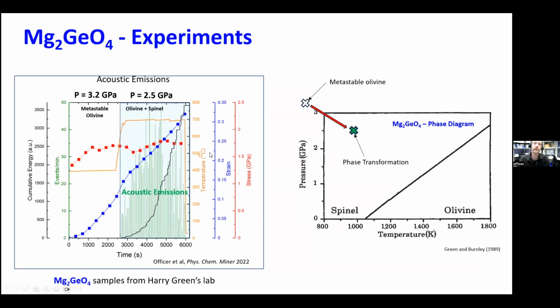So here's an example of a typical Mg2GeO4 experiment. This is one that I ran, but Alex Schubnel was the first to do this in 2013. So I don't want to say that this is the first time this has ever happened. But basically what we're doing is we bring it up to pressure, about 3.2 GPa, and then we've heated it up to 400 degrees Celsius. The temperature is shown in orange here.